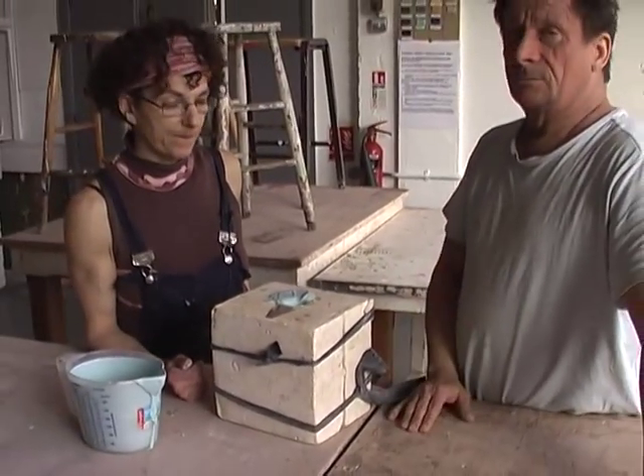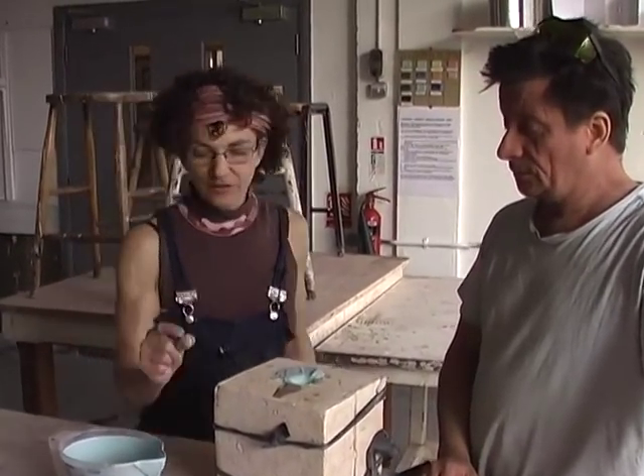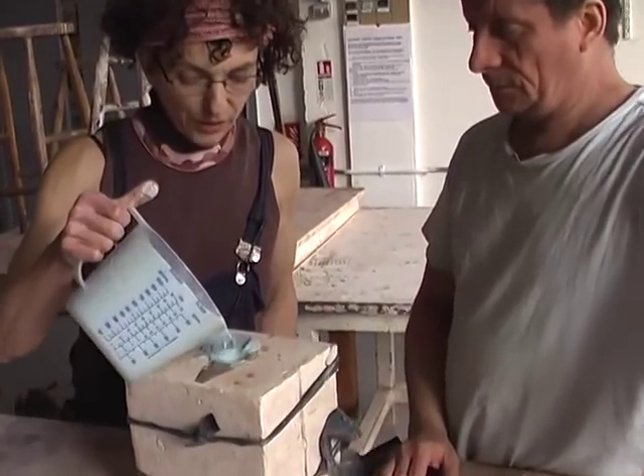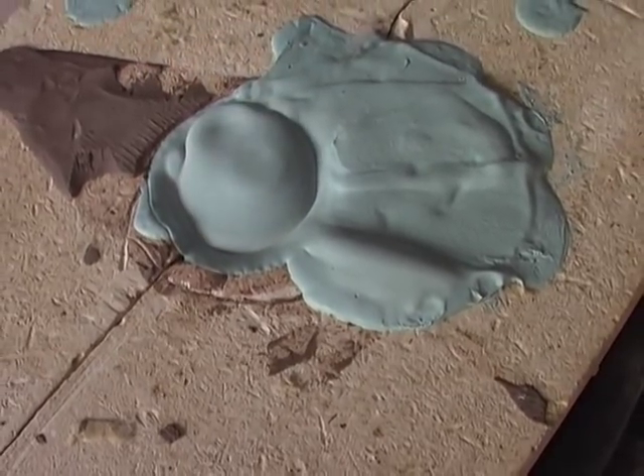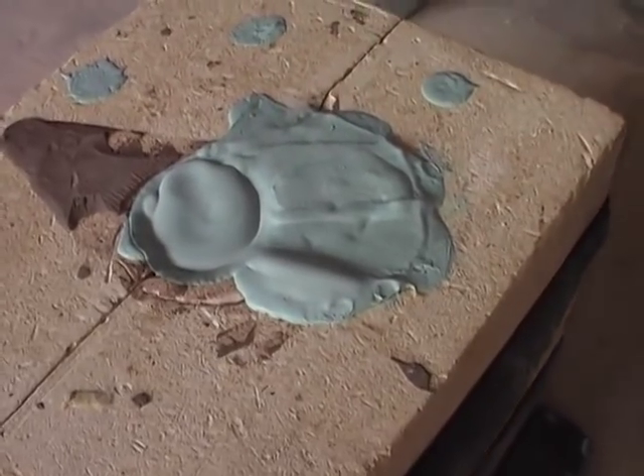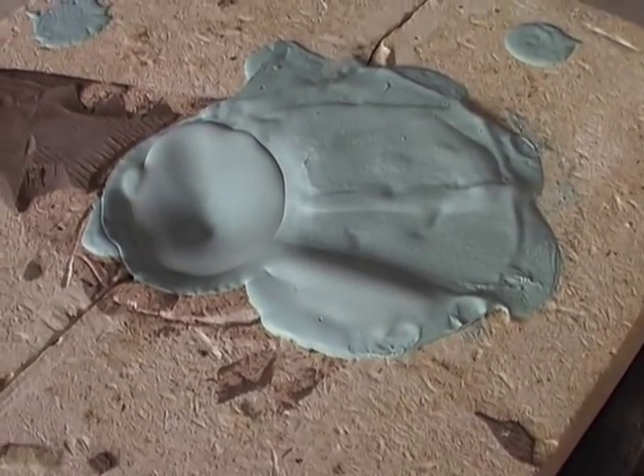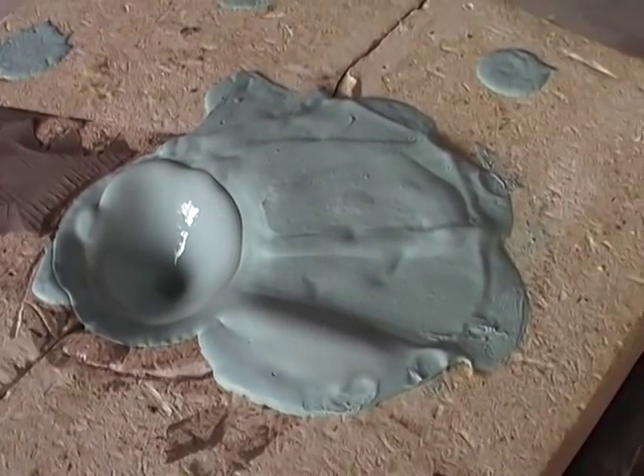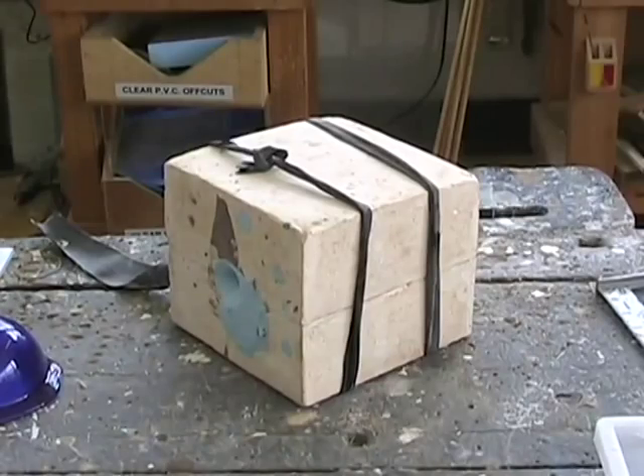How do you gauge the thickness of the wall? Well, it's just experience really. Half an hour gives us a fairly thick wall. You could do it less, but we're not worried about how thick or thin the wall is. This really demonstrates how quickly the absorption is taking place - it's like sucking it from the outside, and if you watch the centre, it starts sinking almost immediately. And as it dries, it becomes matte - see when it's dry, it loses that glossy surface.